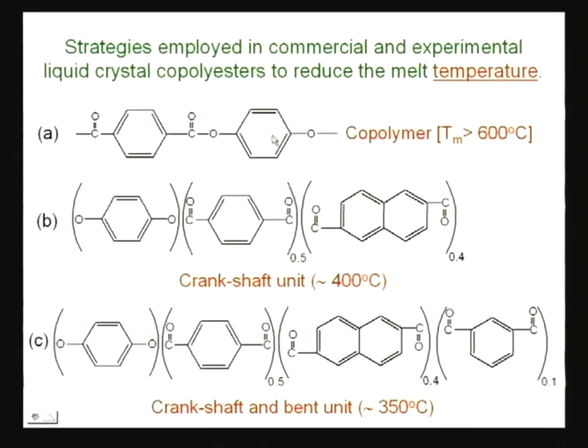Now, you see here this is a polyester made from terephthalic acid and say 1,4-dihydroxybenzene. It forms a polyester. Because of this molecular symmetry, 1,4 linkage, melting point is higher than 600 degrees Celsius, and that too you have to heat this polymer in inert atmosphere, either in nitrogen or helium or argon. Otherwise, if you try to melt this polymer exposed to air, it will degrade, decompose prior to melting. That means, you cannot visualize its melting phenomena. In order to visualize its melting phenomena, you have to heat this polymer under inert atmosphere, and that is again higher than 600 degrees Celsius.